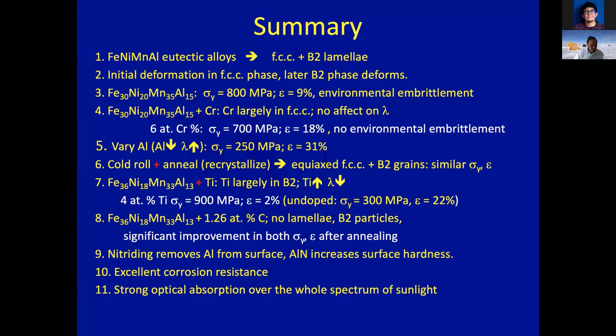So let me summarize all the work that we've done on the eutectic alloys, and then I can answer questions from people. We've got these iron, nickel, manganese, aluminum eutectic alloys, which turn out to be FCC and B2. When you deform them, initially the FCC phase deforms. As it hardens, later the B2 phase will also deform. The yield strength we get for this material is about 800 MPa with about 9% elongation, but it shows this environmental embrittlement effect.